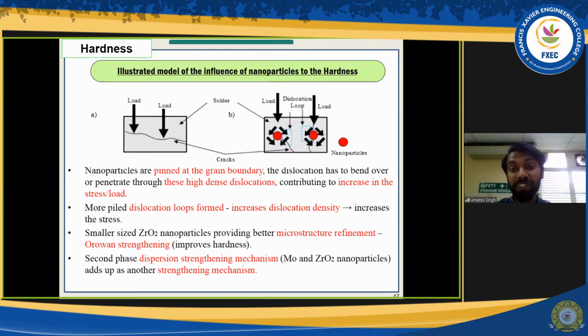They have a higher surface area. So the load has to loop over them. So as more and more loops are formed, the dislocation density increases. Therefore, an increase in the load is needed to break the bond. So this is the reason for the hardness increase from the nanoparticles at the solder area.